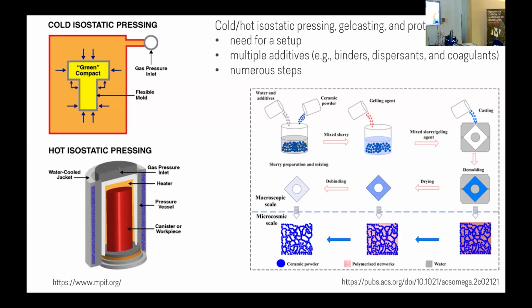On the other hand, you have your ceramic particles, right? And you would like to have a soft matrix in order for the green machining to work. That is how green machining is, right? You have this thing you put into the CNC. So what people do is they create a matrix around those ceramic particles. How do you create a matrix? You can initiate a polymerization around those particles, and then you end up with a polymer ceramic composite, right? That is actually ceramic particles suspended in an organic matrix. Usually acrylamide is used to provide that kind of matrix, and that is a toxic monomer.